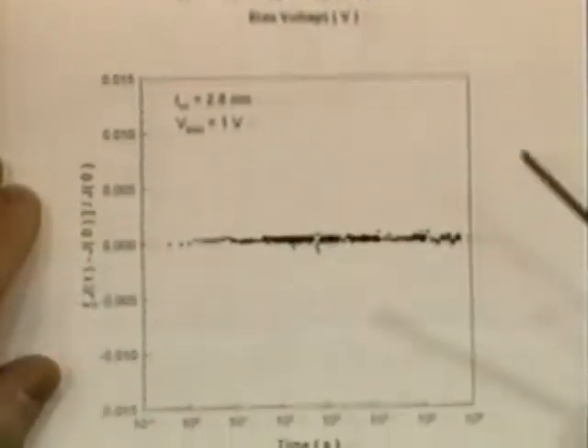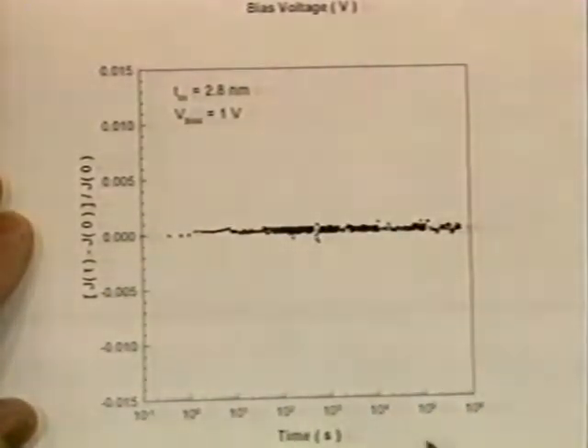And that's why I show in this lower plot here. Fractional change in the current versus time sitting at 1 volt on a 28 angstrom oxide, and it just doesn't change. There's a threshold. It's about 1 volt for the creation of this damage. If you don't put 1 volt across the device, you don't create the damage.